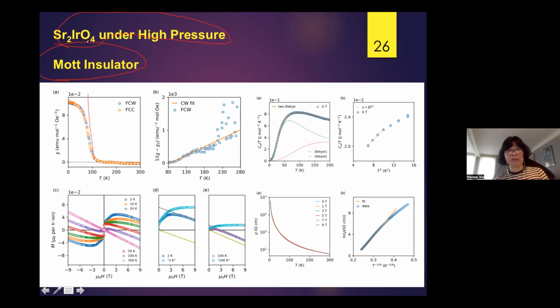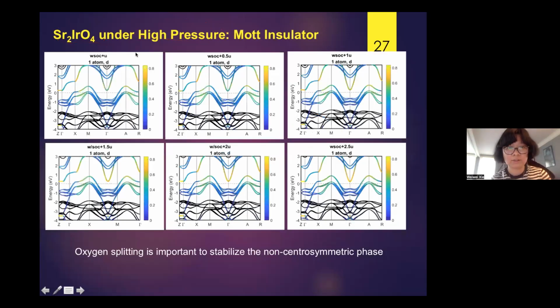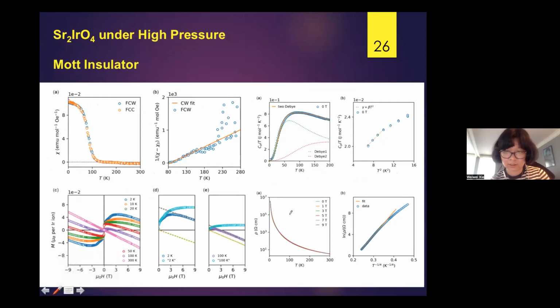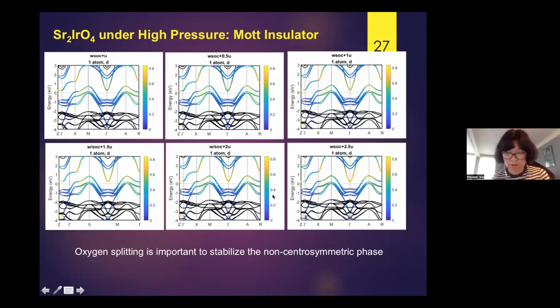Then we did some calculations to confirm this is a Mott insulator. There is one question: no matter what kind of calculation we do, no matter how big a U parameter we add into the system, we still couldn't make it metallic. In the calculation, you see here, it's an insulator. So we think the oxygen splitting really makes this not the perfect material for superconductivity. So nowadays what we are doing is trying to dope lanthanum and barium into the system, also under high pressure, and see what will happen. Can we induce superconductivity?